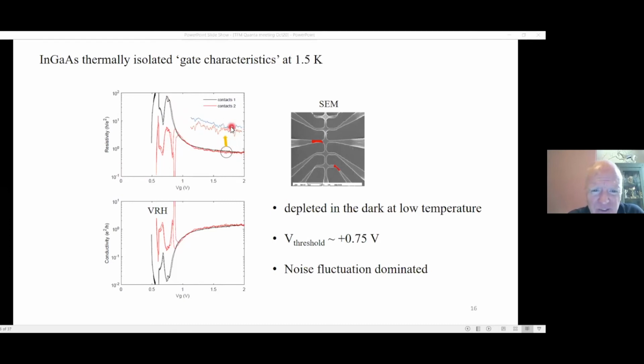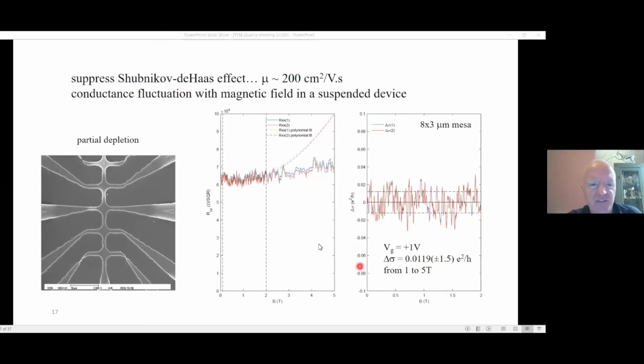If we look in detail, we see conductance fluctuation here. This is completely reproducible. This is from both sides of the device. So from measuring contacts on the left-hand side and the right-hand side, it's usually a good indicator that it's not noise, but actual fluctuation in the signal when they agree. I can also plot conductivity here, which is just 1 over resistivity. Resistivity comes down. We start to lose contact. So the reason we get this signal here is we start to lose contacts. But actually, this has been quite useful because the device is already in that variable hopping regime where you want it in the dark at 0 gate voltage. But we're dominated by noise fluctuations in this system.